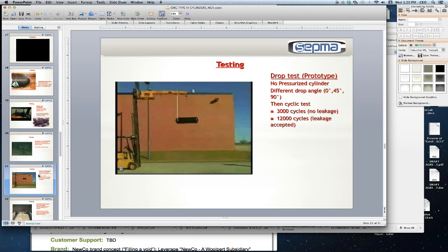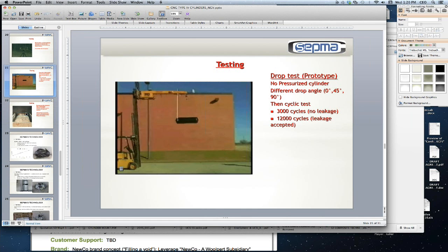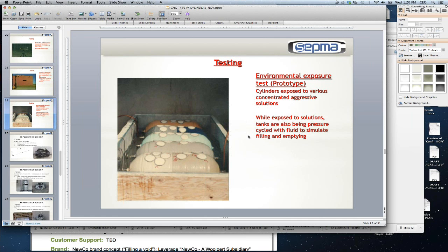Another type of testing is known as drop test. As you can see, you can use a forklift and then drop it from several feet of height. These are done also at different angles. There has to be a certain resistance of the product to impact, and that is to simulate primarily accidents. Finally, another testing is typically environmental exposure, which includes acid attack, salt water attack, and whatever could potentially cause stress corrosion of the system. And this is how it will typically be tested.